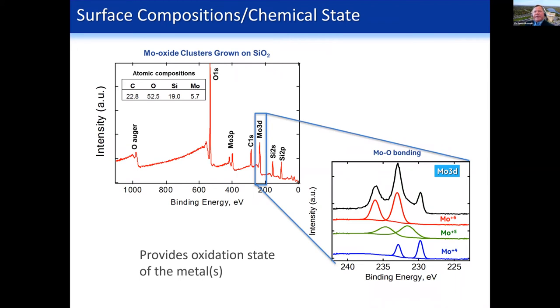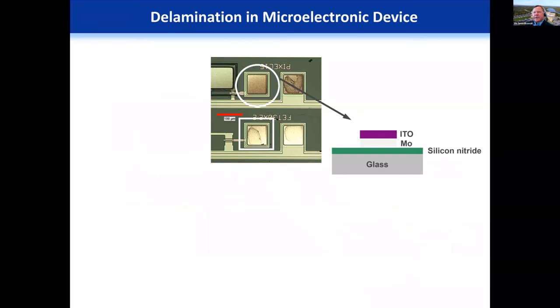The same approach applies for inorganic systems. Here a molybdenum oxide cluster was grown on silicon dioxide. Through the spectra we find the main species present, but our colleague needed to verify the oxidation states of molybdenum in this configuration for cluster growth. From deconvolution of the high-energy-resolution spectra, we determine how much of each different oxidation state is present, allowing customers to verify they obtained what they needed and optimize their processing.